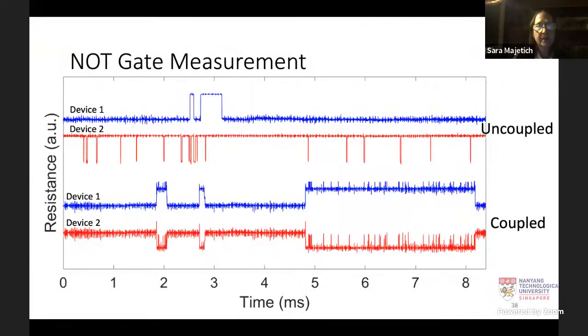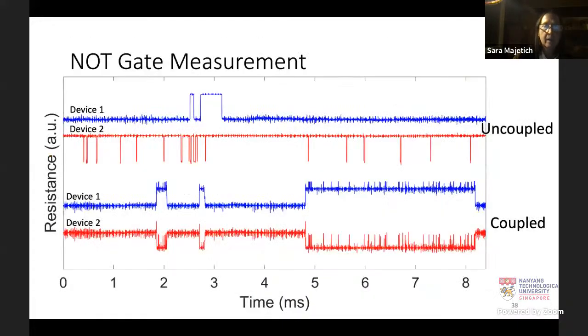And we can see this experimentally with the simple case of the NOT gate. If the 2 devices are uncoupled and we've got different programming voltages, so device 1 is spending most of its time in the parallel state, low resistance, once in a while goes to high resistance, anti-parallel. Device 2 is spending most of its time in the anti-parallel state, once in a while drops down to parallel, but they're uncoupled. And you look over different time windows and there really aren't any correlations, it's random. But you hook them up together, and now we see that when device 1 is in the low resistance state, device 2 is in high resistance, and vice versa. And 95, 98% of the time, we've got this anti-correlation that you would expect, just like you would have for the logical NOT operation.